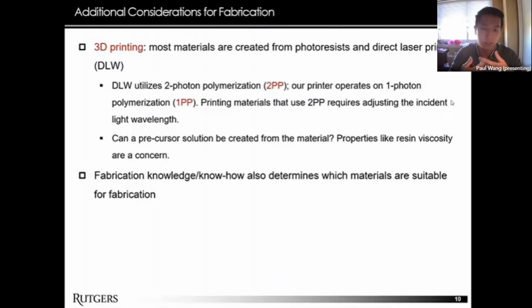There's additional considerations we have to take into account though. Using the radar charts isn't the only consideration for fit. I mentioned before that most of these materials are 3D printable, but they utilize a different type of 3D printing from a lab called direct laser writing, or DLW. DLW relies on a different physical process called 2-photon polymerization, or 2PP. In this process, your printing resin absorbs 2 photons at once to induce polymerization. As a result, your printing occurs in a volume called a voxel, and you have extremely high resolution prints, but the process also requires really short wavelength lasers to accomplish.